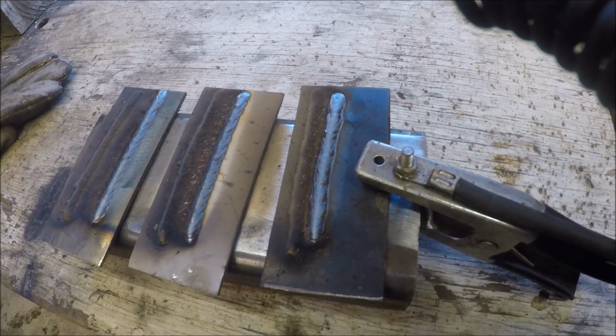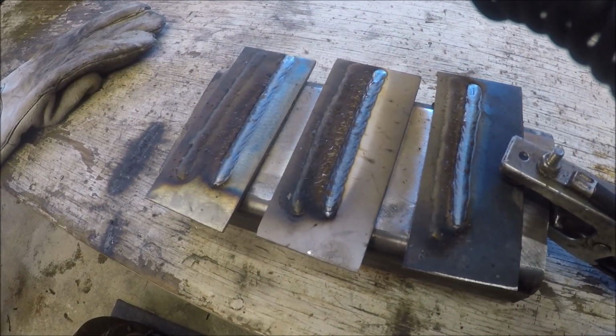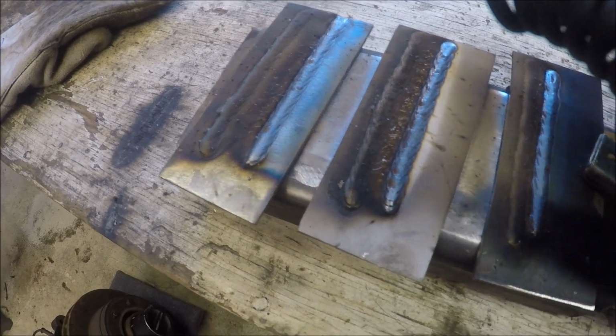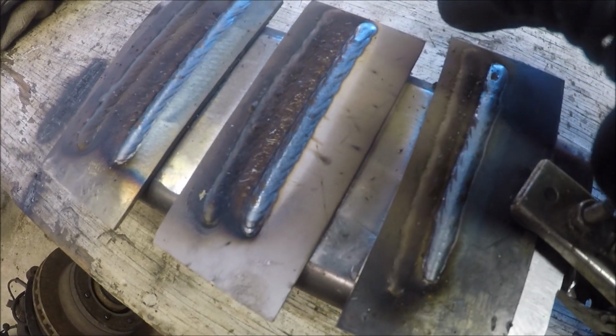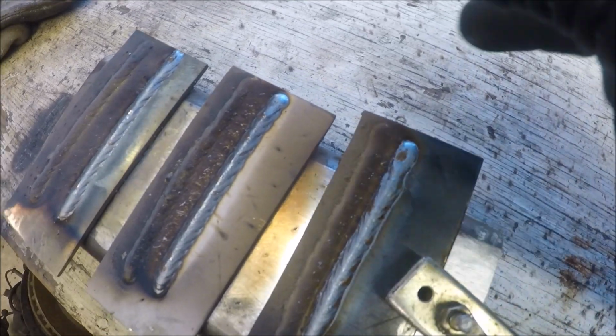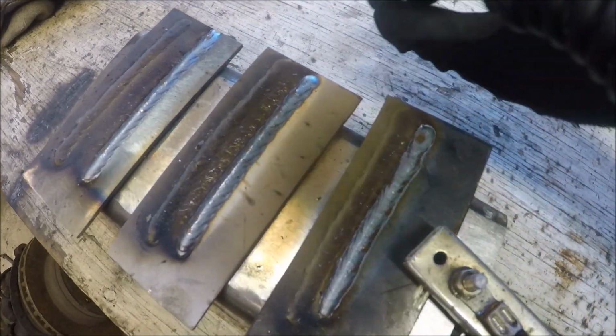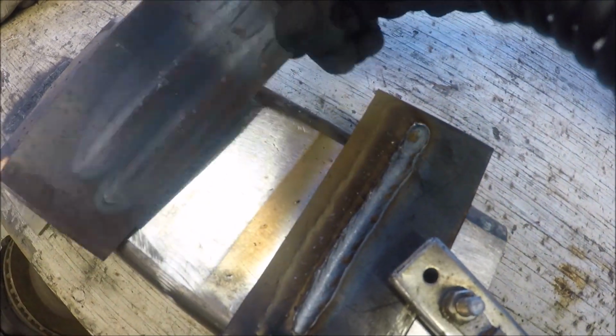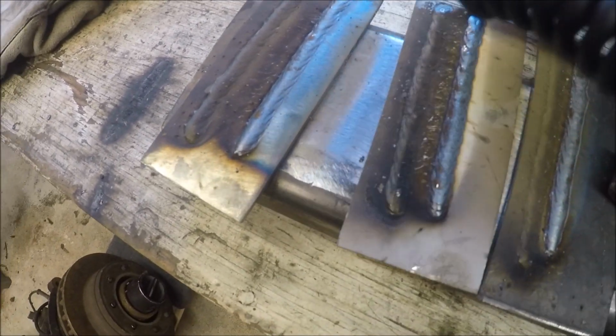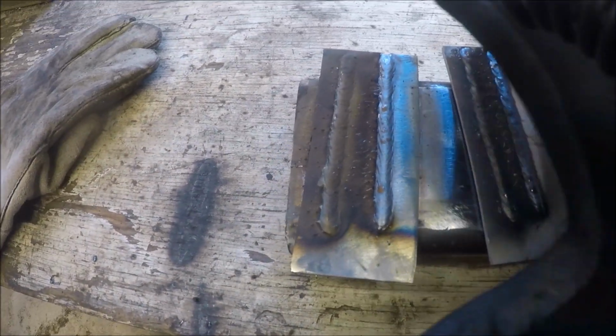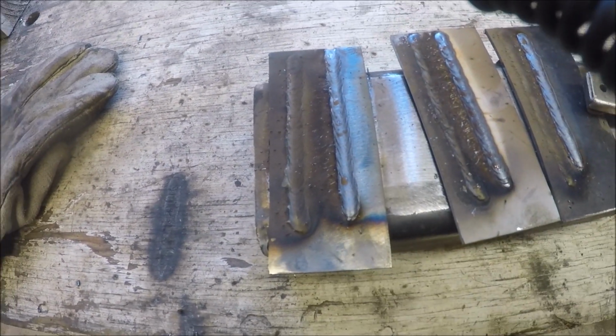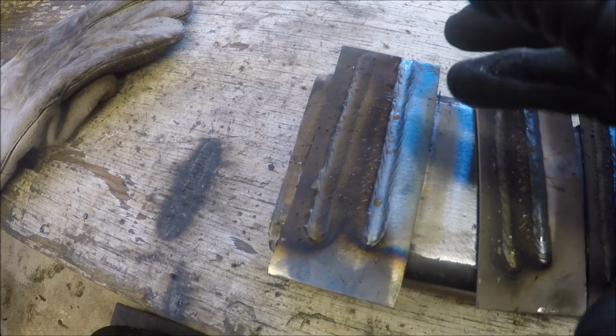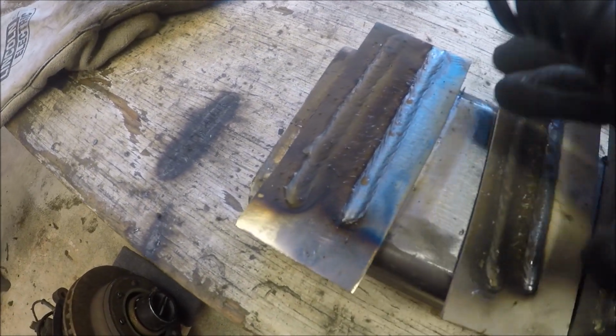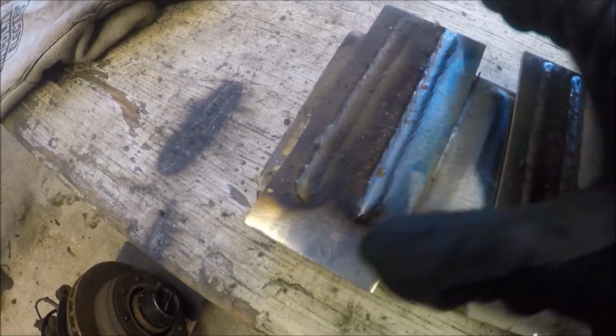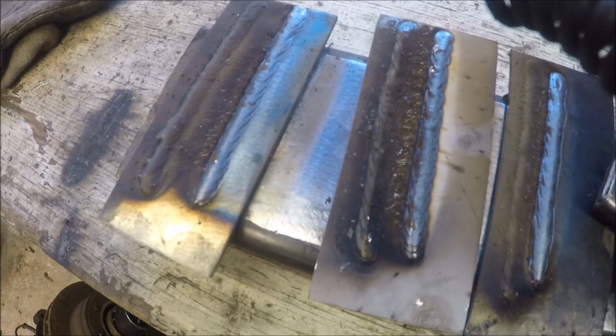Now that second go around, and again, I'm pretty happy with the results. That weld-through primer just does not really seem to be affecting the weld very much. And this is a good, clean weld. Not seeing a lot of porosity. It lays down well, got really good heat penetration. It's still kind of hot. I mean, I'm going to have to have a little grace maybe from the internet welding experts here on my quality of a weld here, but I am really happy. And if you compare it with the clean metal to this metal, it looks really similar.